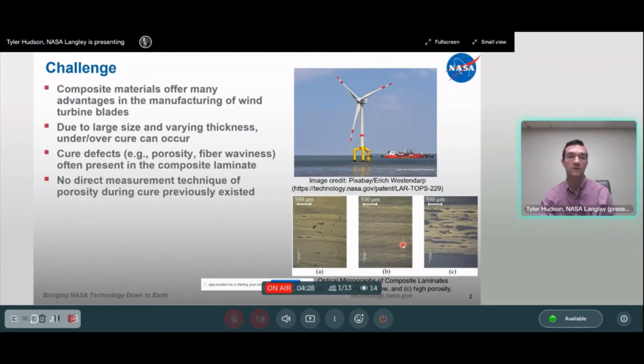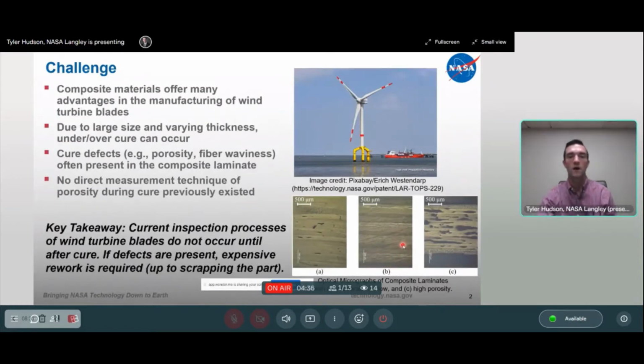Prior to the invention of the system that you heard about today, there was no direct measurement technique of porosity or other defects during the cure cycle. And the takeaway is current inspection processes for wind turbine blades do not occur until after cure. And if defects are present, expensive rework, up to actually scrapping the part, could happen.